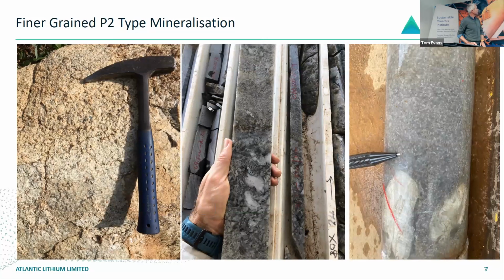And then this is what the finer-grained P2 mineralization looks like here in outcrop. When we first saw it in mapping, back in 2016, we didn't have any experience in pegmatite exploration. We were actually working on gold projects, but we thought these were all granites. But when you took a closer look, you could see all these little blue crystals here. They're apatite crystals. And when we sampled it and the assays came back, it's exactly the same grade as the coarse-grained spodumene pegmatite, but just very much finer grain.